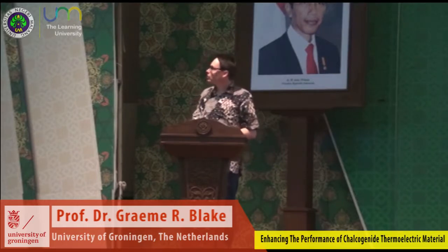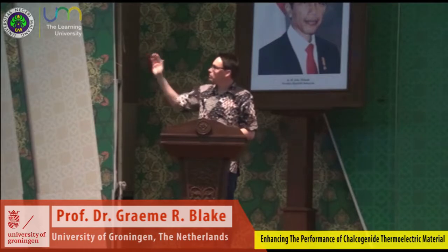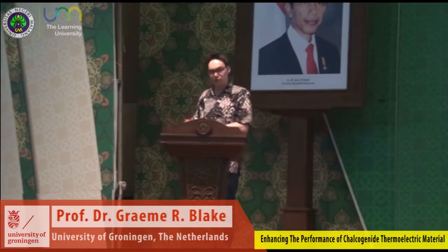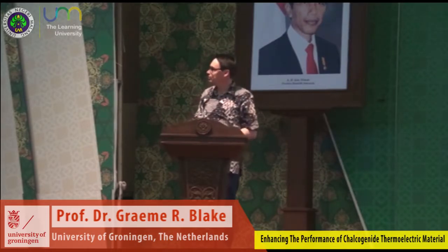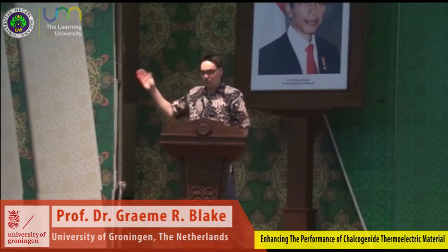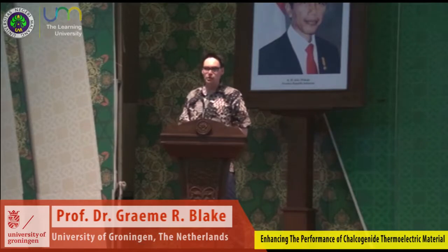Next, please. So we've investigated a few other dopants in our lab, and we found that even greater increases can be obtained with vanadium and with manganese doping. So these are at just 1% levels, but we can obtain improvements in the efficiency by about 50% using these dopants. So we're still doing some experiments to confirm this, and we don't really understand why it happens, but these magnetic dopants seem to give great improvements. So that's an area I think which is very promising to explore in the future. Next, please.